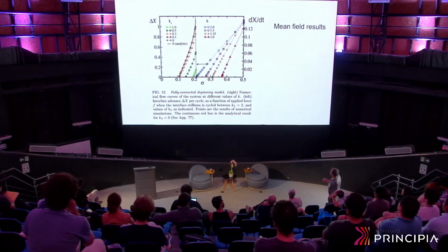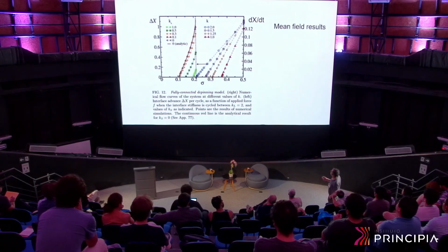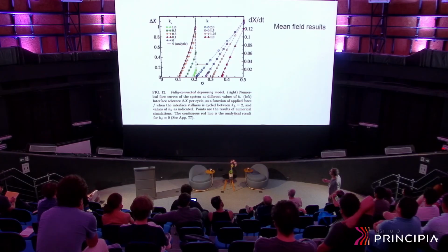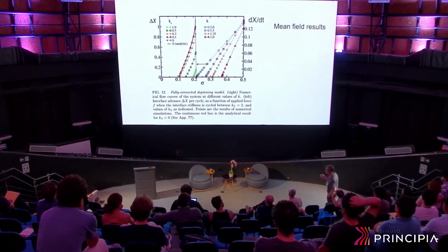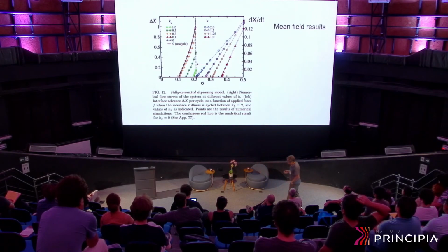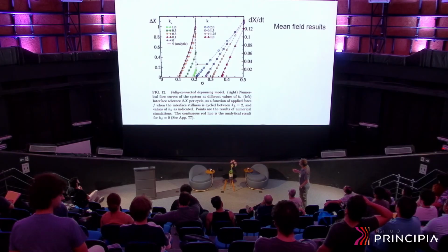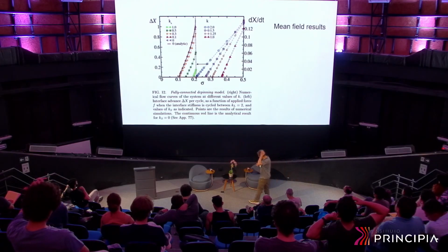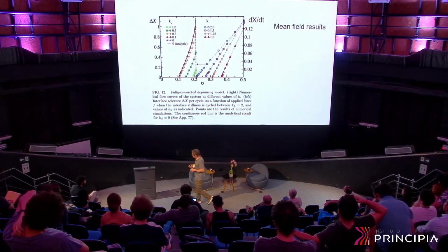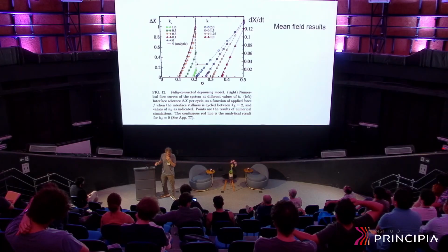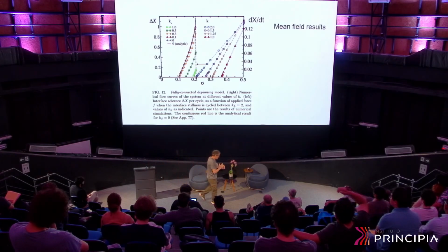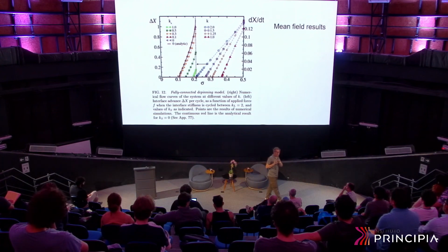And when we cycle the values of K between a large value and a small value, the evolution of this delta X is also linear close to the new critical stress that we obtain here. And actually, we have been able to obtain some analytic form of these curves in this case, indicating that this new critical stress is an analytical feature of the problem. And this is quite interesting because the existence of this new critical stress, we think, is correlated to a phenomenon occurring in another problem, which is in principle different, but in the end probably very related to this, which is the problem of fatigue crack propagation in materials.